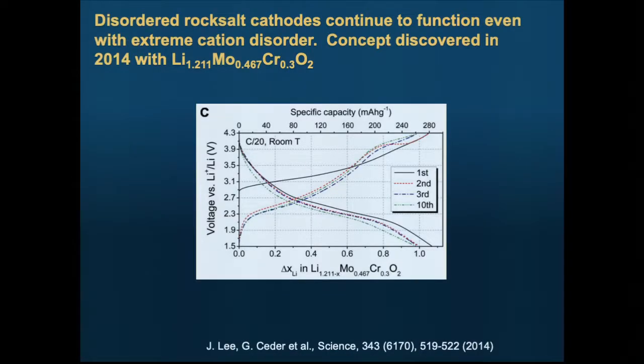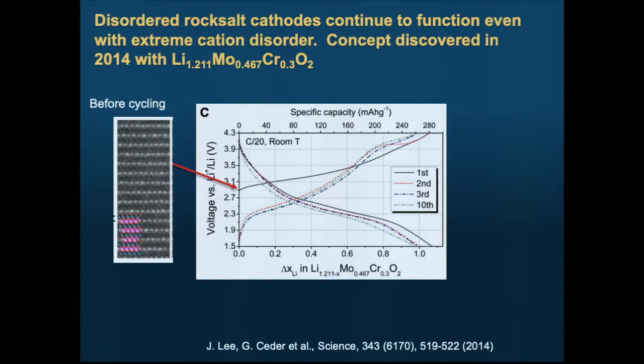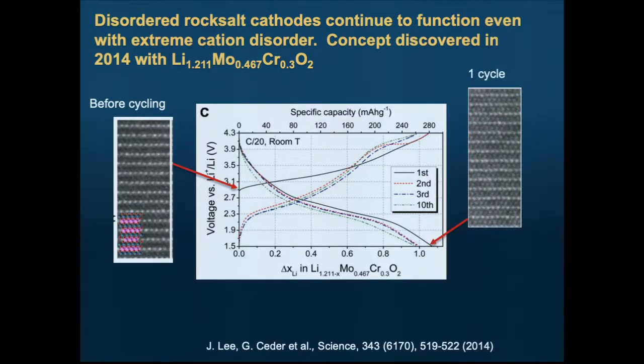So the first material in which we did that was actually a material that started layered. This is a lithium molybdenum chromium oxide. This is a STEM picture. And you actually see the layering, right? Where you don't see anything, that's lithium because it has low Z, right? So this is a well-layered material. This is after 1 charge-discharge cycle.